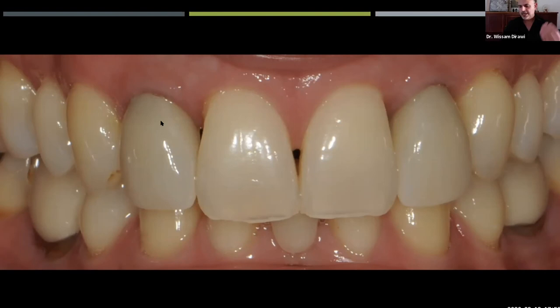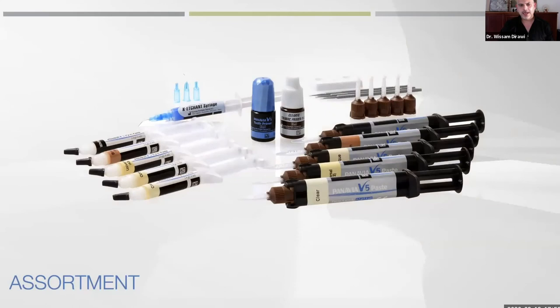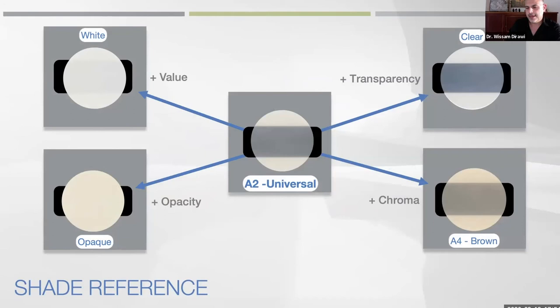of the abutment here. So maybe I should have used the high translucent, the less translucent construction with a little bit of porcelain, maybe here on the upper part to make it look good, but it wouldn't have been that translucent. Or we could have used the try-in paste from Panavia and probably used the more opaque cement to just block the abutment. So that wasn't a very good case, but please, please, please take pictures and speak with your dental technician and use the try-in paste. It's a good thing to use. I didn't use that in that case.